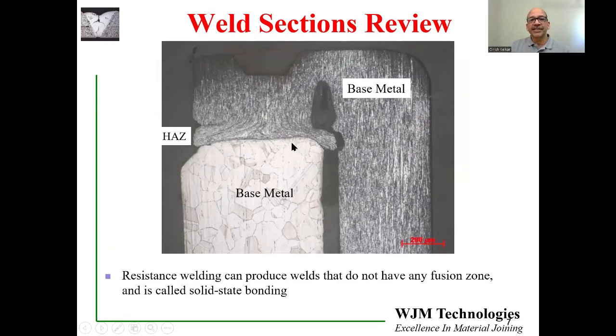Here's an example of a cross-section. Again, this is a resistance weld where the 2 parts have been joined, and the junction is as shown over here, where you can see a distinct line. In this case, the 2 base metals obviously look different, so they are different types of steels in this particular situation. And you do not see a fusion zone along that interface. Now, this is quite interesting and also quite common in resistance welding, where there is no fusion at the interface. There are many other processes, including friction welding, where there is no fusion.